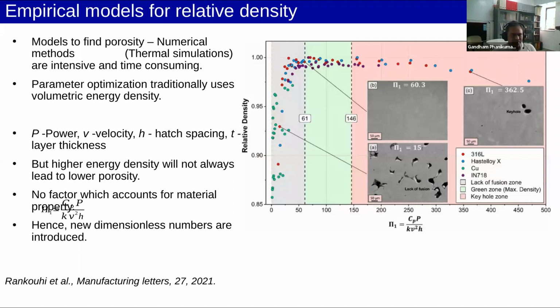It is quite reasonable. However, it doesn't have the physics completely taken into account. So you can use it only as one of the filters for your process parameter variation, but this is not the ultimate because it doesn't give you everything. But you can plug in and see where you are. This is data that has come from multiple alloys, and therefore it's fairly good, and it is available as an empirical correlation in the paper.